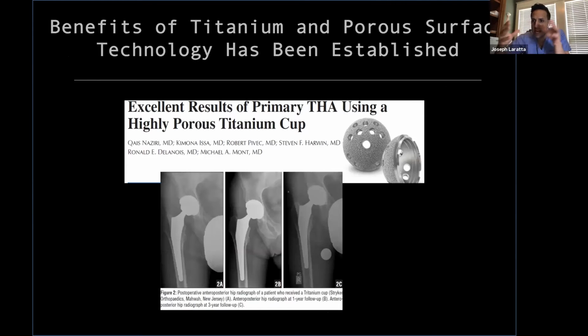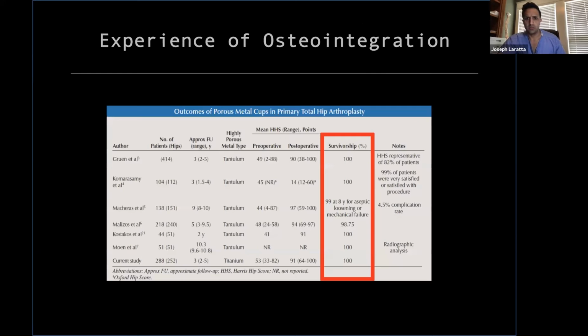The benefits of titanium and porous surface technology in terms of osseointegration is not new, right? This has been around for a long time, particularly in orthopedics. We've used porous titanium for total hip arthroplasty for about 30 years. And it's been used even longer in dentistry. So when I actually looked to see who used the first porous titanium, dentists were using it for implants like 50 years ago, again, to get these tooth implants to fuse into the mandible.